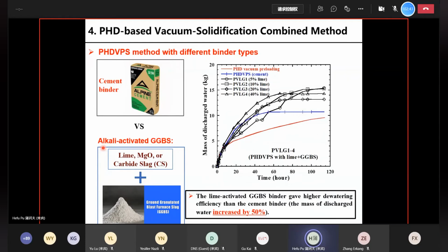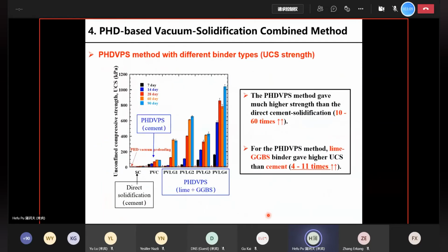This figure shows the mass of discharged water, and the blue curve is for the cement as a binder, and the black curves are for the lime activated GGBS. And you can see that more water was sucked out. The mass of discharged water can be increased by 50% when we replace the cement binder with GGBS binders. And because of that, the strength was also increased significantly. On the figure, you can see that the proposed PHDVPS method gave much higher strength than the direct cement solidification. The increase is about 10 to 60 times. And as for the binder, the lime GGBS binder gave also much higher strength than the cement binder. The increase is about 4 to 11 times.